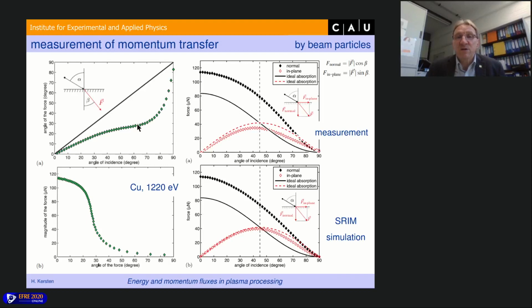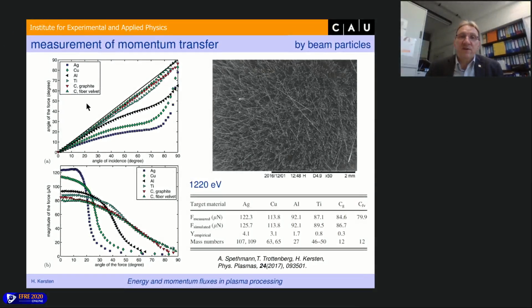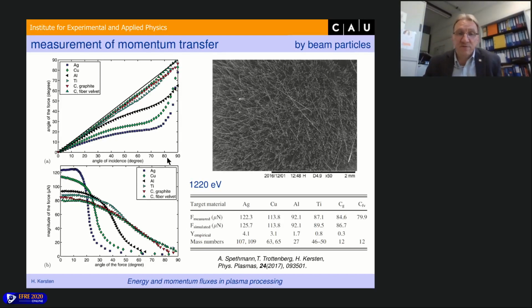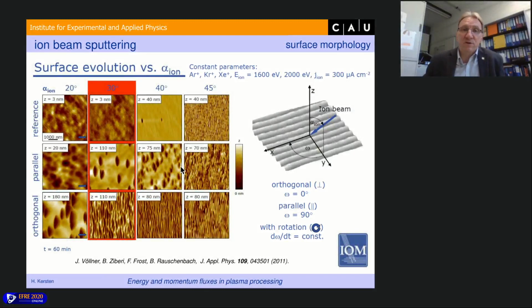And this can be determined very accurately for the different materials. For instance, as you can see here, we have several materials, different metals, and carbon. And this is a carbon fiber velvet where all particles stick. And you can see this is almost on this line. That means there's no sputtering and no reflection. All incoming ions or fast particles stick into this material. But if we use silver or copper, then we have a lot of reflection and sputtering, and we have a strong deviation from this line. And by this, we can calculate the sputtering effect or the reflection effect of the ions. This is important, for instance, to know this angular distribution if you want to sputter special structures like ripple structures or chevron-like structures if you rotate your substrate.